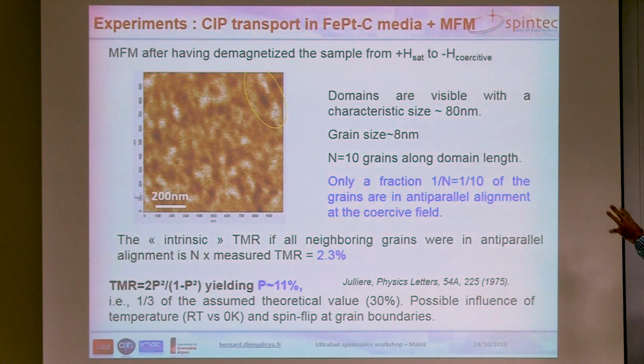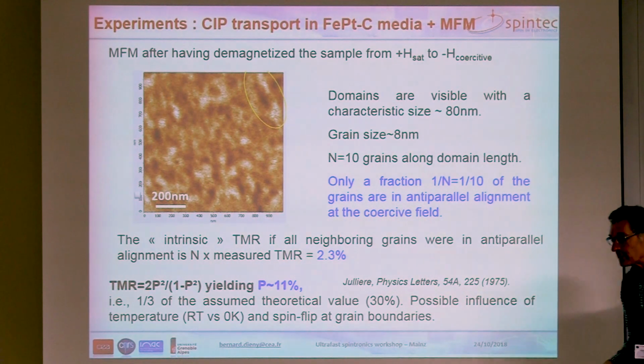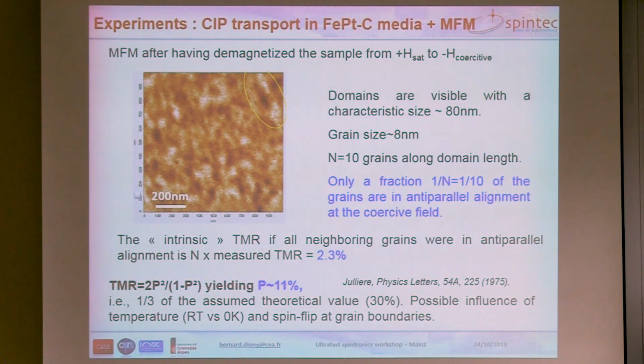And if we correct for this dilution effect due to the fact that we have only 1/10 of the grains which are in antiparallel alignment, we can deduce that the intrinsic TMR of two neighboring grains in switching from parallel to antiparallel will be 2.3%. It's still not very high, but considering this expression of the TMR as a function of the polarization of the tunneling electrons, this means that the polarization of the tunneling electron is 11% here. In the theory, with the parameters that we chose, we determined 30% of spin polarization, and experimentally we found 11%, so 1/3 of the theoretical value.